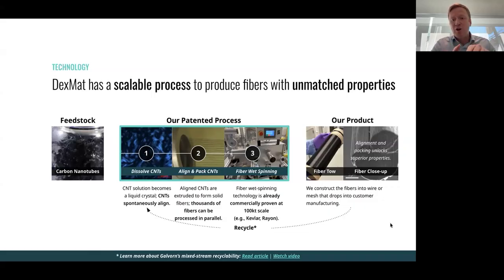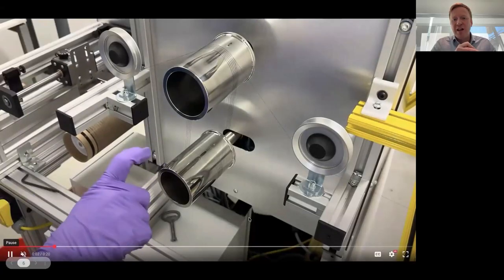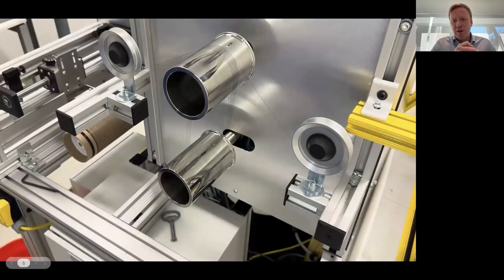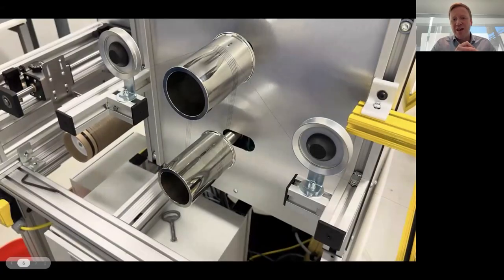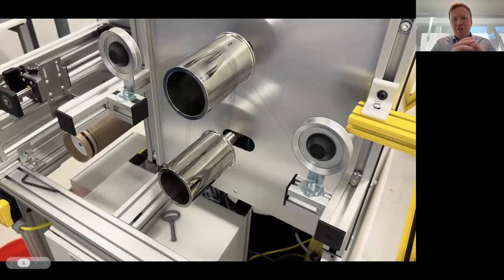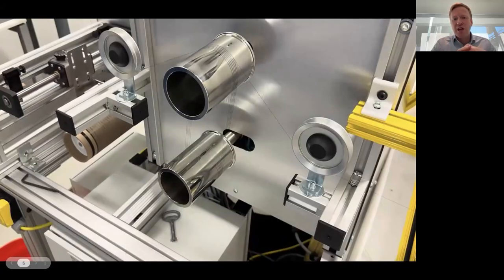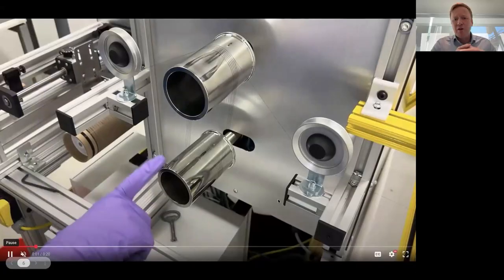And as I mentioned earlier, we can take the fibers after they've reached end of life and put them back into our solvent in step 1 of the process and recycle them to make Galvorn again with no loss of properties. Next slide. Here we are showing just a portion of our production line, the collection point of the fibers. We can't show you the entire machine because it contains some proprietary information, but this shows the speed at which we are able to collect our fibers, which is actually faster than the production speeds used for things like PAN carbon fiber precursors. If you go to the next slide.